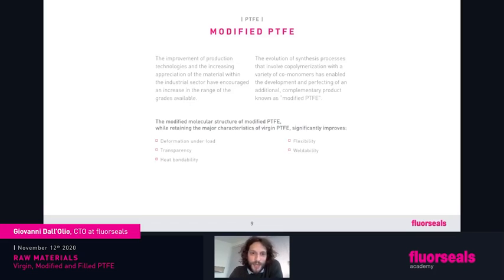I promised you that we would see the modified PTFE performance. So we already mentioned that modified PTFE is a change of the macromolecule of PTFE with this ramification. But why do we have to use modified PTFE? Basically because this ramification leads to some better performance compared to virgin PTFE. We will have a better deformation under load. One of the problems of PTFE is probably the deformation under load. That means it doesn't resist very high loads because the linear chains want to slip one over the other. So this ramification of modified PTFE will help it to have a better deformation under load.